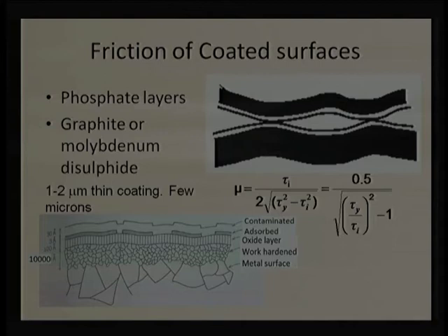That is more than sufficient, but we know very well there will be some wear of this lubricant layer, and we do not want the lubricant layer to ever turn out to be 0. So, we generally keep a few microns, it can be 10 micron, 15 micron, depending on the life of the component and whether we are going to use liquid lubricant along with the solid lubricant or not. If you are not using any liquid lubricant, naturally we need to keep a slightly thicker layer, so that the component can be refurbished after a certain number of operating hours.